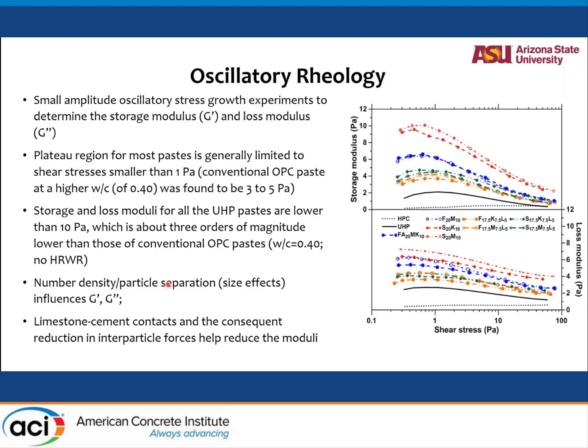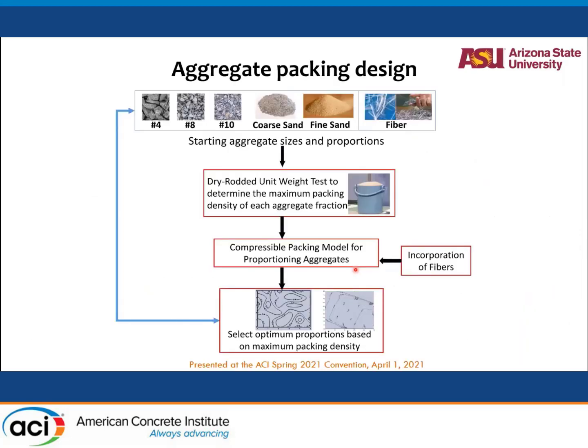Number density, particle separation, all of those influence G' and G''. Limestone cement contacts and the consequent reduction in the particle forces. We have some zeta potential measurements, which I'm not showing now, but having shown that limestone cement contacts help reduce the oscillatory shear moduli. Okay, so now we have the paste all set.